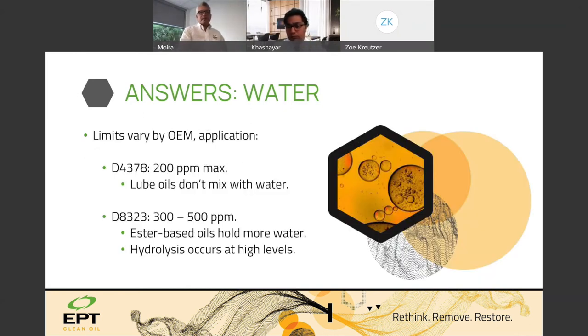The limits for water vary by the application. I would refer to ASTM for how much water is my limit in this application, and I also look at my manufacturer's in-service limits. In a steam turbine oil system, the first 50 ppm is going to be dissolved. You're not going to get free water probably till 200 ppm or higher, and I could be wrong on that point. But free water would normally easily separate from the oil